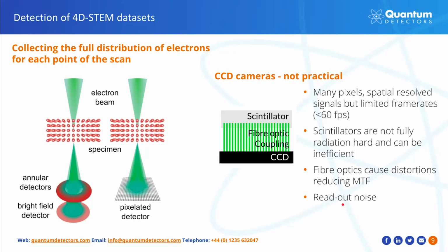Microscopy users have always strived to learn the most about their samples, but technical limitations of past detectors have reduced the information available. Standard STEM detectors are able to collect data with megahertz frequencies. However, the information from the momentum space, as I said, is averaged into a few numbers. For a long time, the only way to access this information were CCD cameras. However, they're strongly hampered by their maximum speed and their efficiency. A practical limit of 60 frames a second in a CCD camera is very limiting, especially if the sample is drifting in the microscope or there are additional problems going on.